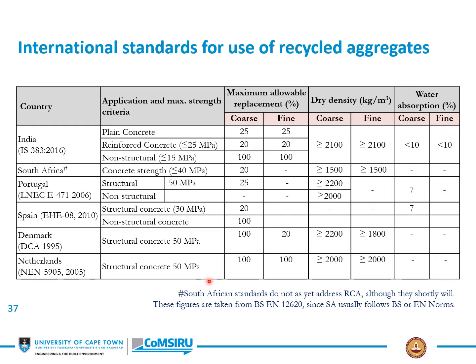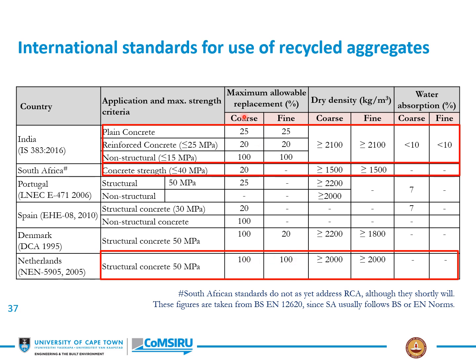Now here are some standards just to show you what is available for the use of recycled aggregates, and there are a whole series of countries given there. Looking at India, you can see that for non-structural concrete, up to 100% of both coarse and fine aggregates are acceptable. In reinforced concrete, at this stage, only 20%. In plain concrete, 25%. On the other hand, if we go to the Netherlands, or South Africa, there we're a little bit behind, only 20%. But in the Netherlands, you can use up to 100% of both coarse and fine. And clearly they've made great progress here and know how to beneficiate and use their material to the greatest extent.